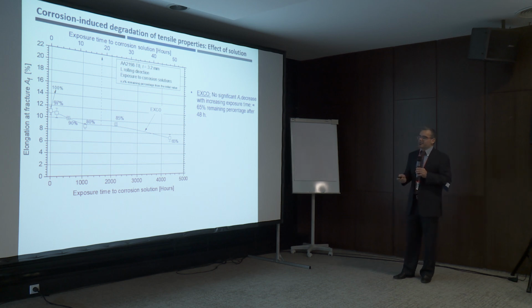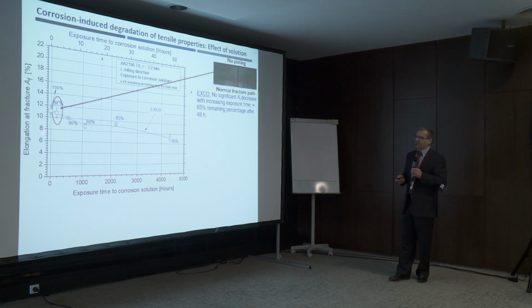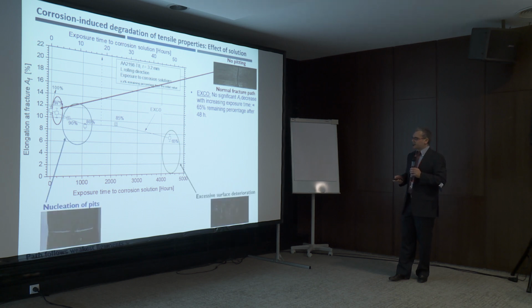I will sum up with the elongation at fracture for all these three different solutions, starting from the EXCO. Here you can see the scale in the upper bar. So you can see a gradual degradation of elongation at fracture, with areas of no pitting, some nucleation of pitting, and of course extreme deterioration after 48 hours, I suppose after 24 hours.